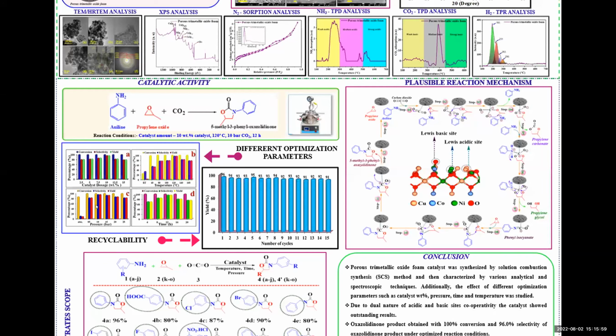In the effect of pressure, at room temperature and atmospheric pressure, the reaction failed to achieve the desired product. When the reaction was performed at 10 bar, the desired product, that means the oxazolidinone, was achieved at 96%. When the pressure is increased up to 25 bar, due to the high solubility of carbon dioxide in the reaction medium, the selectivity of the desired product gradually decreases. In the effect of time, the catalyst showed good results at 12 hours reaction time. Catalyst achieved 96% yield and selectivity.